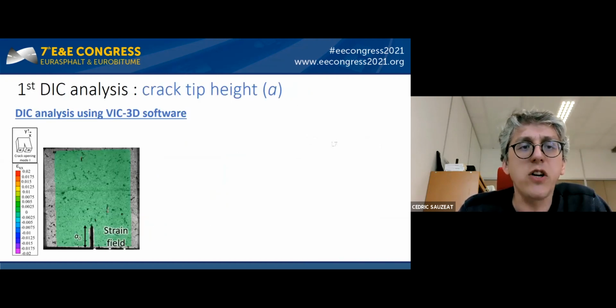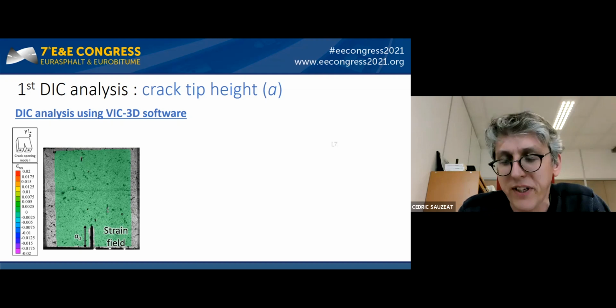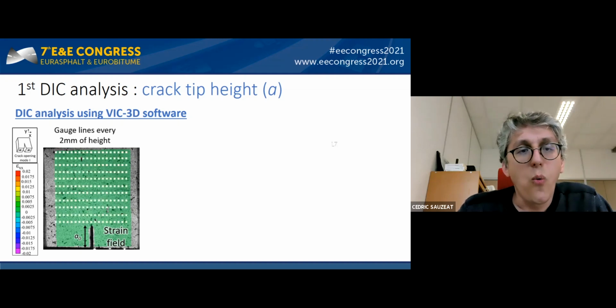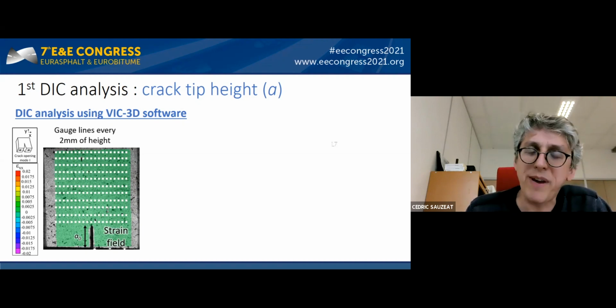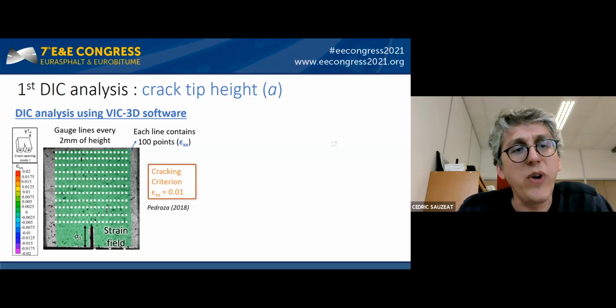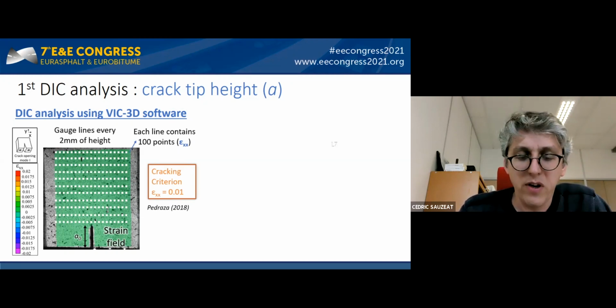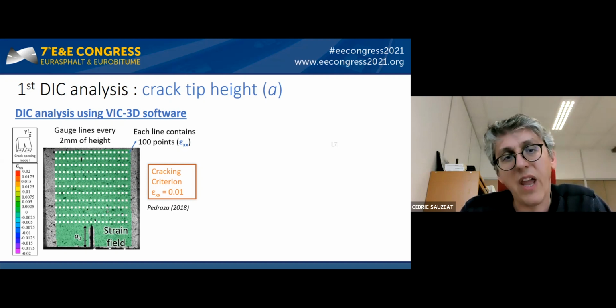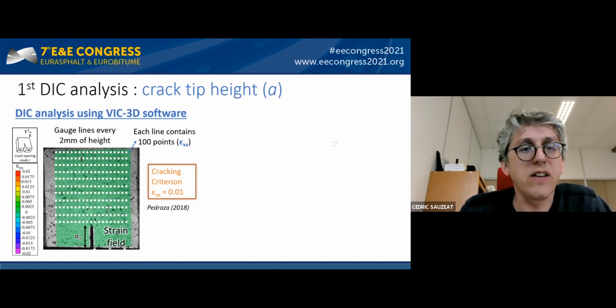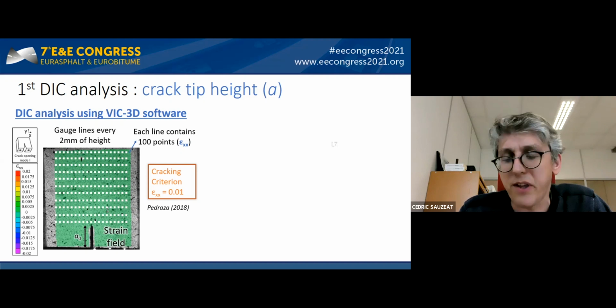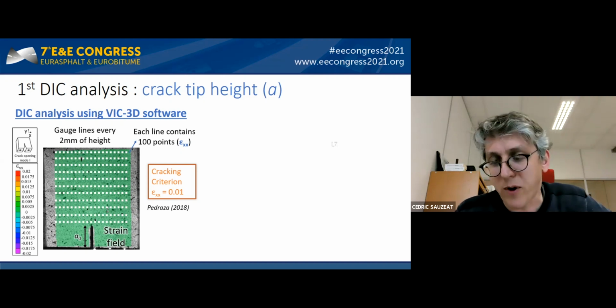Concerning the digital image correlation, we performed 2 analyses. The first analysis enables to determine the crack tip heights during the test. So we plot virtually some lines in the height of the specimen, and along each line, we analyze the evolution of the strain, so longitudinal strain, epsilon XX. And to determine when the crack crosses the line, we fix a cracking criterion. When the strain reaches 1%, we consider that the crack has crossed the line.